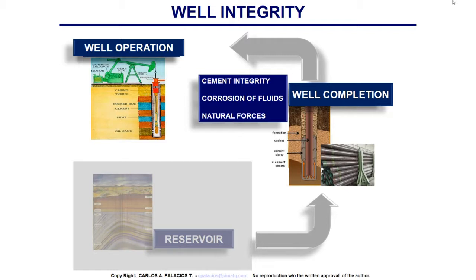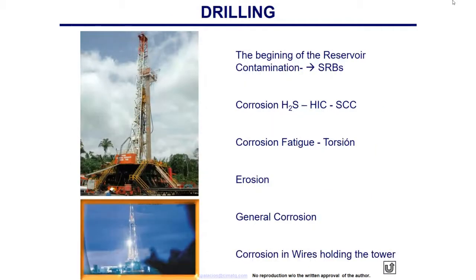And of course, from the get-go, they don't treat the water properly, for the same reason I just mentioned. Oh yeah, well, we use chlorine dioxide. All right, chlorine dioxide reacts immediately, but it doesn't have any residence time. When it goes into the reservoir, no more biocide is in there. So we need to come up with proper techniques to treat that water, especially the millions and millions of gallons of water that we use in the fracking in the unconventional wells. So drilling begins on the reservoir with contamination because of the lack of treatment.